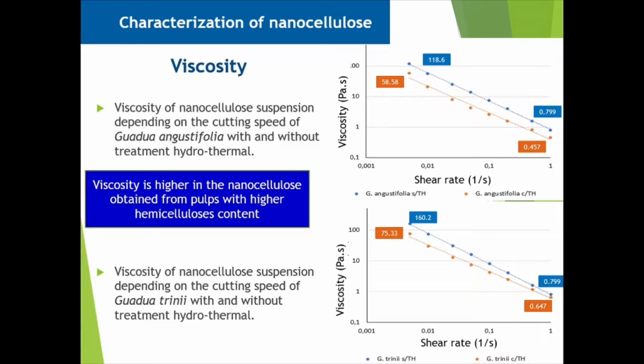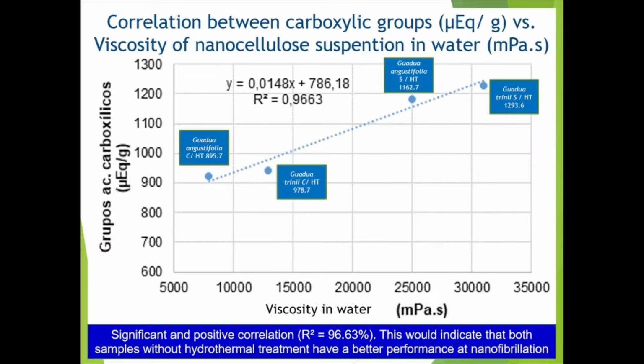Viscosity of both species was determined using 100 milliliters of the sample at 0.3% consistency at 500 rpm for 60 minutes at 25 degrees. The graph shows the viscosity values versus the shear speed. For both species, the viscosity is higher in nanocellulose obtained from pulps without hydrothermal treatment due to a more significant hemicellulose presence. They have a higher yield of nanocelluloses and a greater capacity for the individualization of nanofibers.